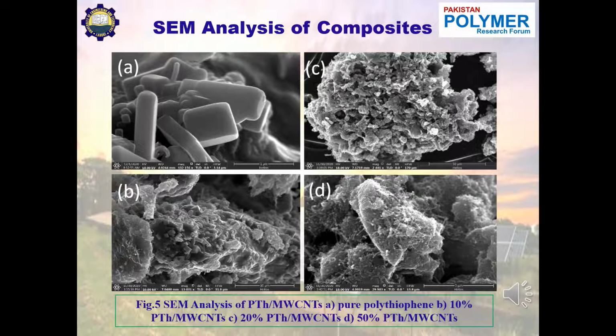Figure B explains the structure with 10% MWCNT dispersed in polythiophene. The dispersion of MWCNT is achieved to some extent, and we can see the improved morphology of polythiophene as compared to figure A. In figure D, 50% MWCNT polythiophene depicts that the dispersion achieved was not as good as that obtained with 20% MWCNT. Morphology obtained was better with 20% MWCNT as compared to all the above figures.